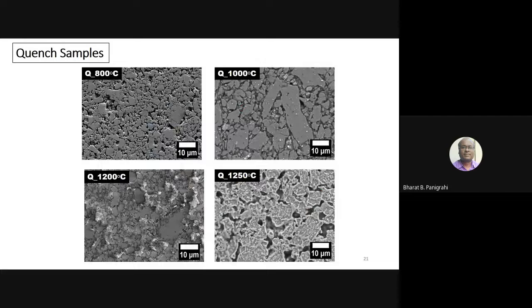These are different temperatures. You have quenched the material at 800 degrees Celsius, and you can see there is no sintering at all. At 1000 degrees, there is a little bit of sintering and grain coarsening. But at 1200 degrees centigrade, you will see that some fraction is where liquid started forming.